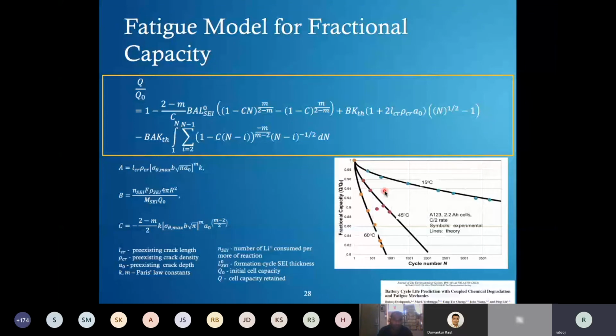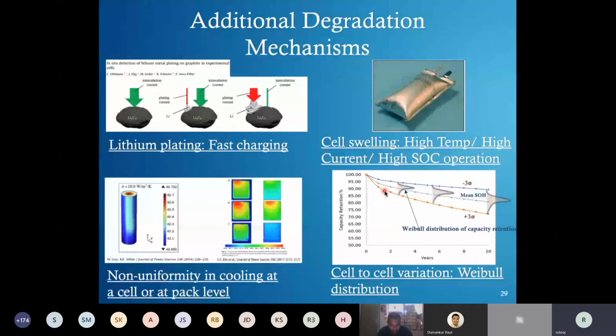Now there are additional degradation mechanisms such as lithium plating. If you're trying to charge your cells at really high rates, specifically when you're already close to fully charged, so at higher SOCs, higher state of charge, you may see that the lithium, rather than intercalating, will just plate, it will just deposit on the electrode particles. And as soon as it deposits, it basically reacts.